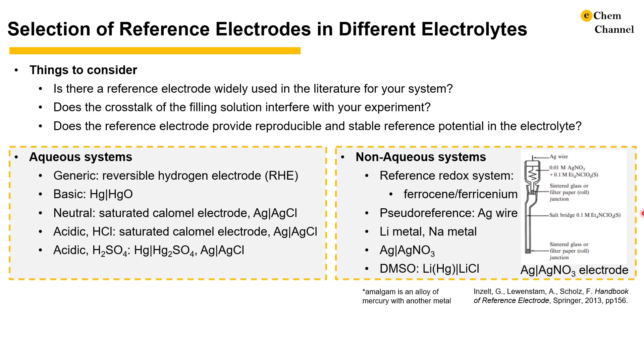In non-aqueous electrolytes, we don't have a general standard reaction like the oxidation of molecular hydrogen. A common standard reaction is the ferrocene/ferricinium ion couple. In systems where a pseudo-reference or quasi-reference electrode like a silver wire is used — because we don't know its exact potential — the potential should be calibrated against ferrocene/ferricinium ion before reporting values. In energy storage research, alkali metals like lithium and sodium are frequently used as reference electrodes. Other common options include silver/silver nitrate in acetonitrile. Since silver ions can react with some solvents, a different reference electrode such as lithium amalgam/lithium chloride in DMSO may be used in those systems.